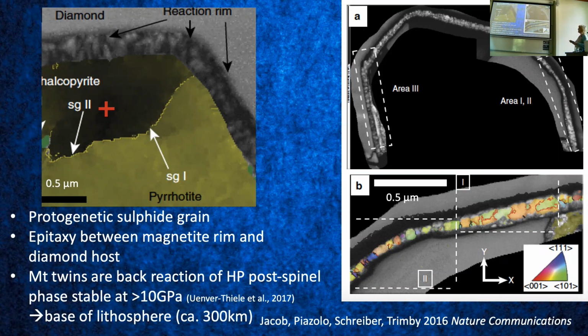But the good thing is that this reaction rim was thinned to an extent that we could study it better. Then we got really good EBSD or TKD data on this reaction rim and found that it is magnetite, consisting of all small nanocrystallites. We could get orientation data for these nanocrystallites, and we could also see that they were twinned. So these were twinned little magnetites forming a reaction rim around a sulfide in a diamond.